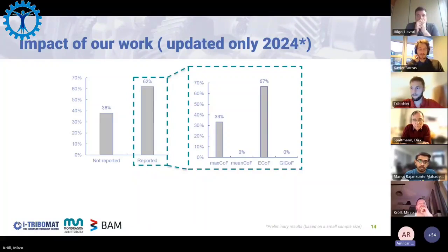But in fact, in several cases in fretting, we cannot speak about a friction coefficient. Especially when you do not have real sliding involving the surface, we don't reach the maximum value of the friction coefficient, and so the concept is not applied. Yes, but I was talking about fretting wear, which is a gross-sliding phenomenon. In all the cases that I showed, it was gross sliding.